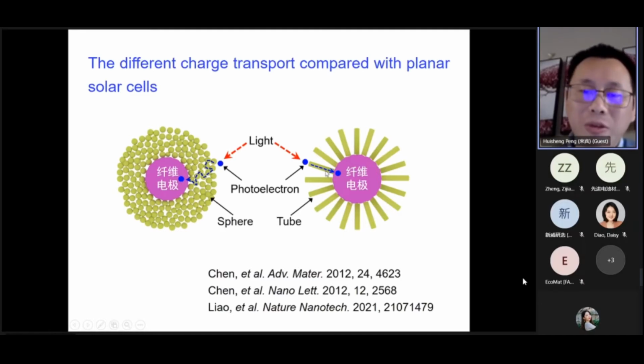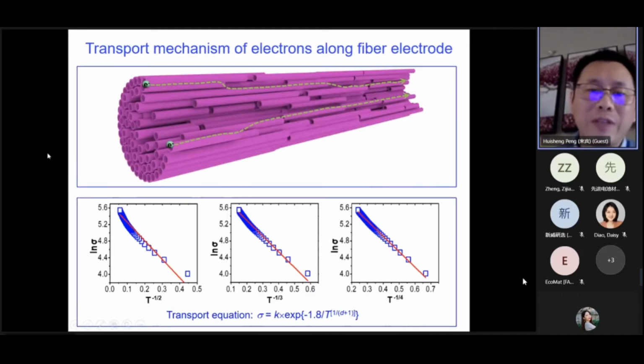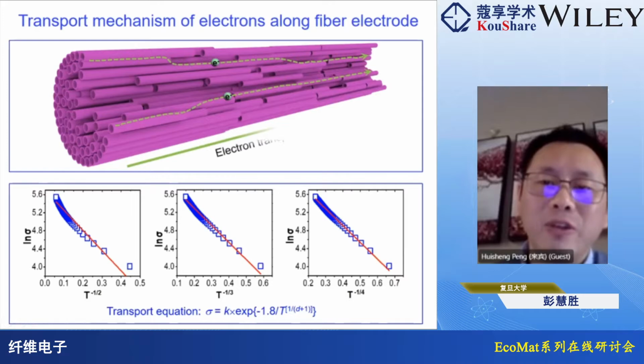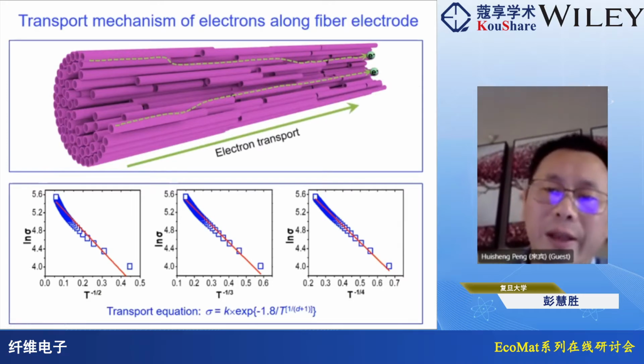So for planar solar cells, people will tell you that this kind of structure shows the highest efficiency. And for our fiber solar cell with nanotubes or nanorods, we find the highest power conversion efficiency. Also, the fiber solar cell is very long, especially for new applications, while in the planar solar cell it's a very short distance for the charge to transport. So we try to understand how charge can transport quickly and efficiently along the long fiber electrode. We show it's a three-dimensional hopping model. I will not go into the details.